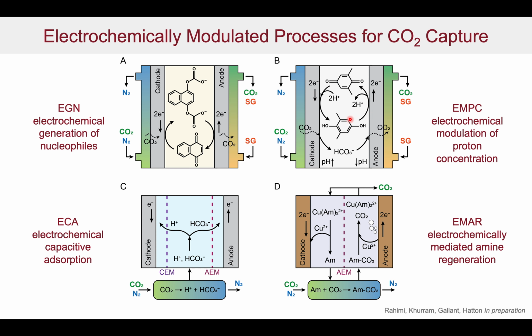The same kind of systems can be used indirectly when we've got protic solvents. In this particular case, when we get the reduction of the quinone, it actually gets protonated rather than capturing the CO2. It captures the protons, and this causes an increase in the pH, and therefore an increase in the CO2 capacity to form a bicarbonate. On the other hand, when this is oxidized, the protons are released, the pH goes down, the capacity for the bicarbonate transforms back to carbonic acid, and the CO2 gets released in this particular case.